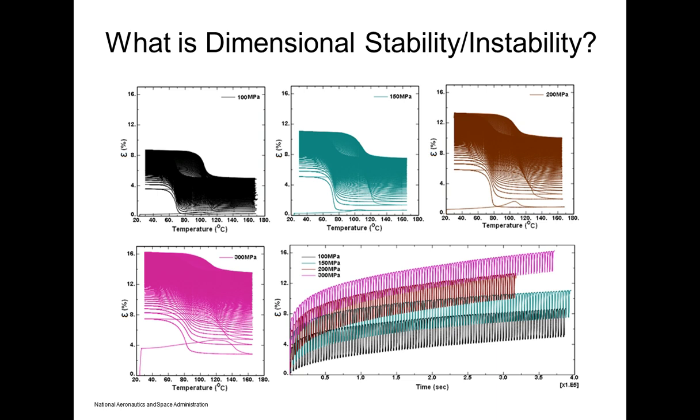Anywhere along that curve, we could pick off both a temperature and a magnitude. So if we did the isothermal deformation process at a given temperature, we just need to know what level of deformation we should be at that temperature. As long as we reach that level at that temperature, we will ride on this final stabilized curve in a subsequent process. So the deformations do not have to be at room temperature, and in fact in a lot of cases they shouldn't. We used room temperature as an indication that it can be done anywhere in the field, because typically we would rather process at higher temperature. We get less damage accumulation when we do that. But the point is, in this system, because of how far these damage mechanisms are pushed out in terms of the strain field, we can process almost anywhere we want as long as we know what that target end deformation state is. I hope that answers the question.